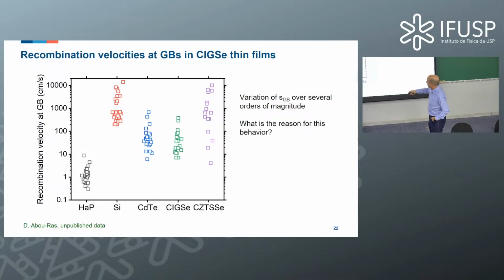Okay, but if we do such measurements on various material systems, I gave you the results here for silicon. These are just examples, not representations for these technologies, okay? But I took out some of the cells which we investigated, and various technologies. It's very interesting. Look, there's a very similar behavior. Always a distribution across several orders of magnitude. Okay? For halide perovskites, I will come back to this case, it's a very small median value, yes? But the others remain more or less on the order of maybe several 10 or several hundred or maybe several thousand centimeters per second, right? But always the same behavior.